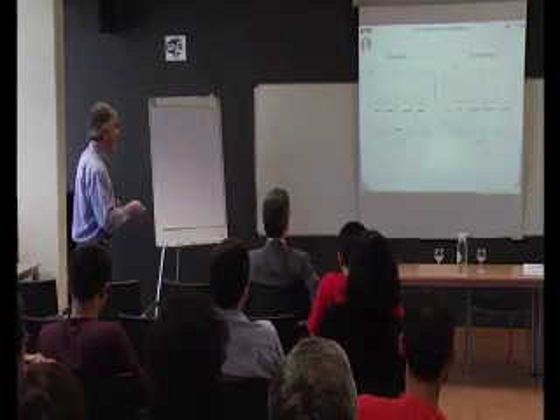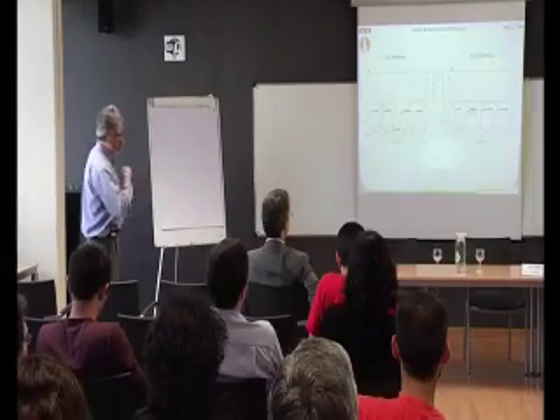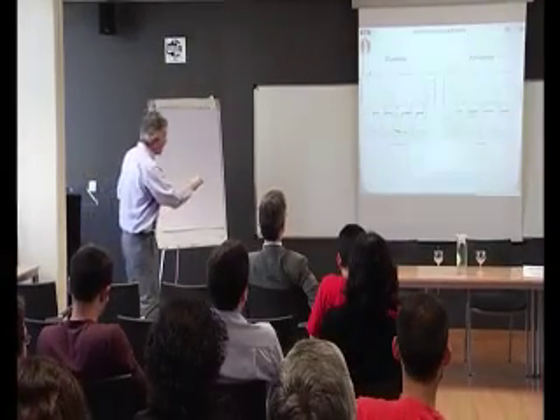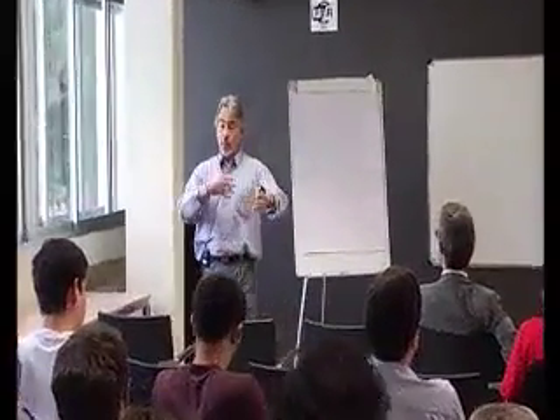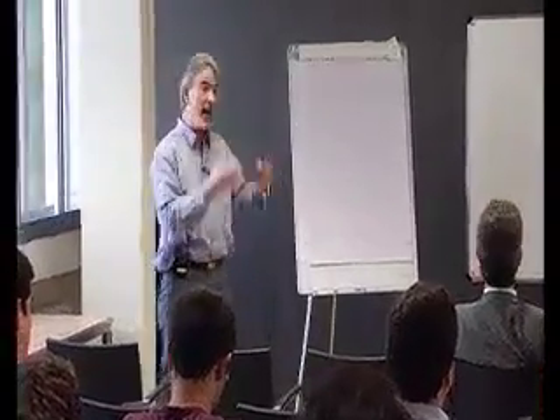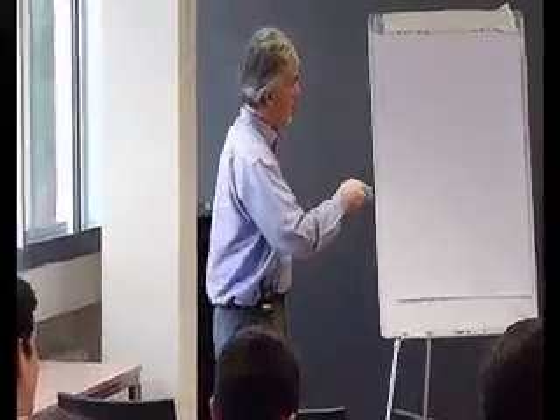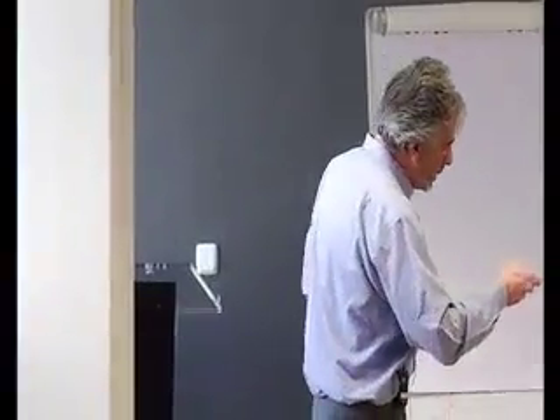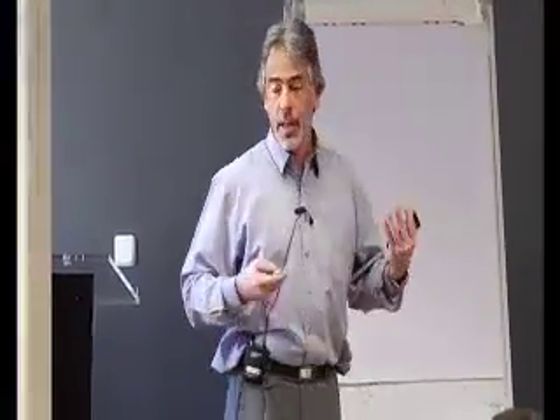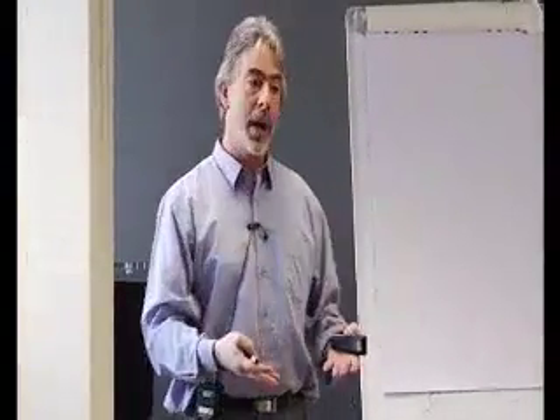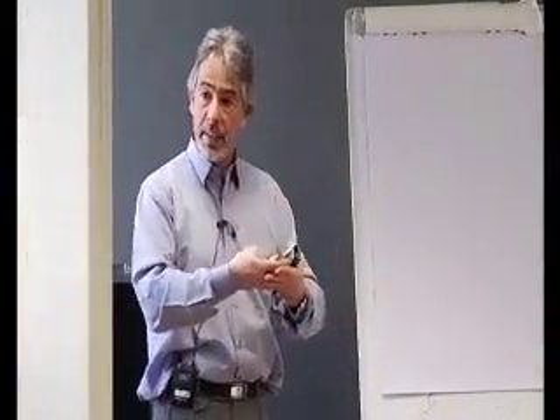We did the same with water splitting. Instead of feeding CO2, now we are feeding steam. Again, the temperatures, and here is the oxygen peak, here is the hydrogen peak, oxygen, hydrogen. Now we integrate the curves of oxygen, we integrate the curves for CO, we take the ratio between the two, we find 1/2. This is correct because when you split CO2, you get 1/2 mole of oxygen and 1 mole of CO. The same here, we integrate the curve of oxygen, we integrate the curves for hydrogen, we take the ratio between the two, we get 1/2. Correct, we are closing the material cycle.